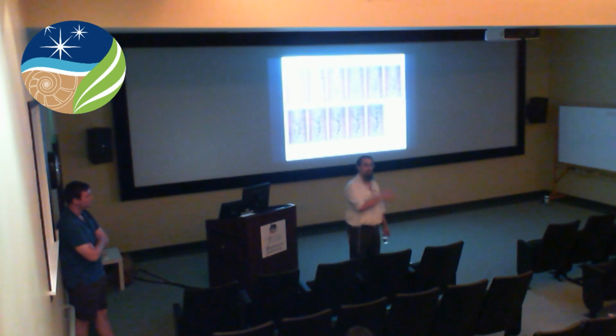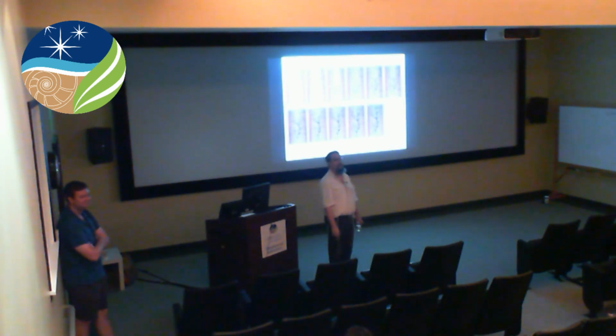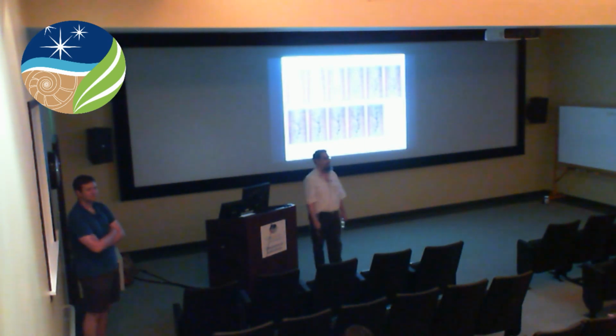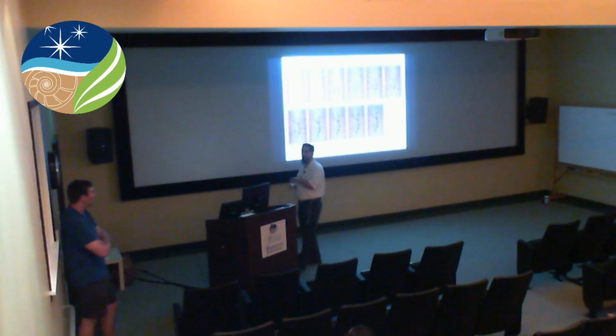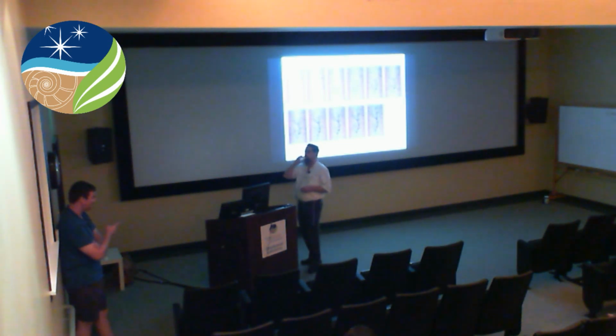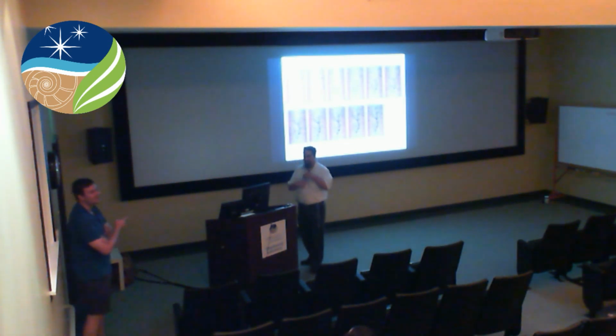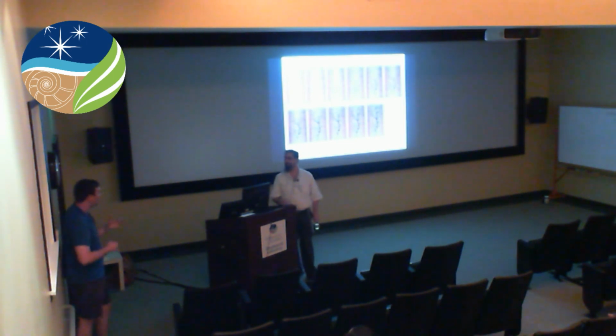If the bulk is changing, there's no obvious paths. But even there, remember when I was talking about how those things fell? We think that it's not really precipitating evenly within the material. Precipitation seems to occur in sandstones in these larger pore channels, and we don't know whether that's because of the thermodynamics or because of the flow. And to do that, you have to have a model where you have easier flow paths, faster flow paths, greater volume paths, and some without that. So the answer is, heck yes, we're working on that, but no, we're not there yet.